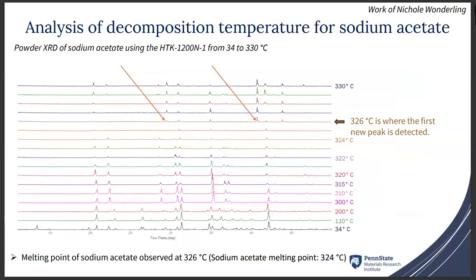This was done as well for the sodium acetate, and it could be seen that the decomposition temperature was around 326 degrees centigrade, where we start seeing a new peak, which is very close to the theoretical value of 324 degrees centigrade.